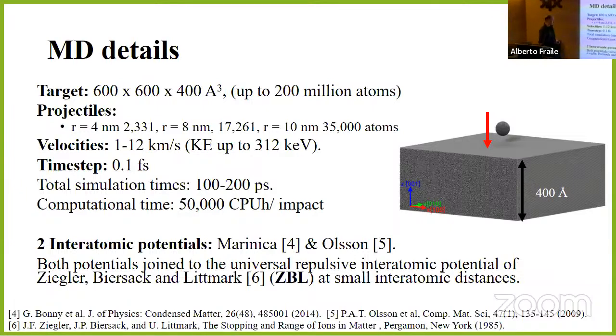We did it with 2 interatomic potentials, what we call Marinica and Olsson. And in both cases, the potentials must be corrected with this ZBL correction. That means that you have to make them a little bit more repulsive at short distances. Otherwise, the impactor at high velocities just goes through the target as if the target were nothing.